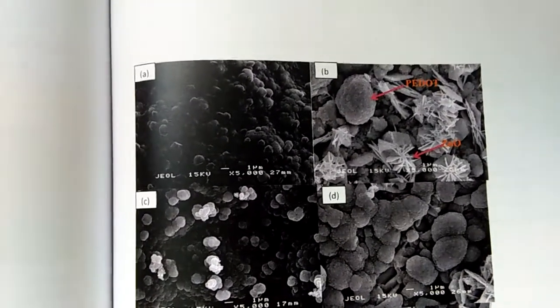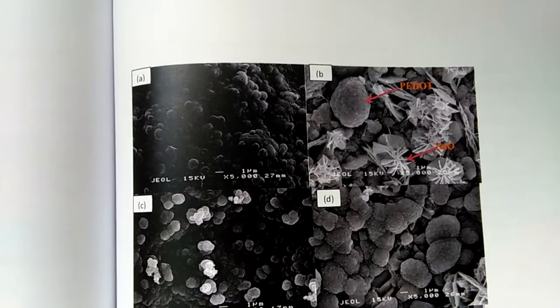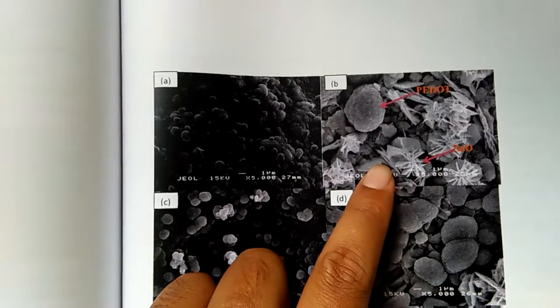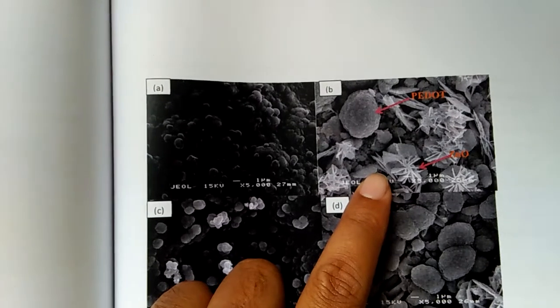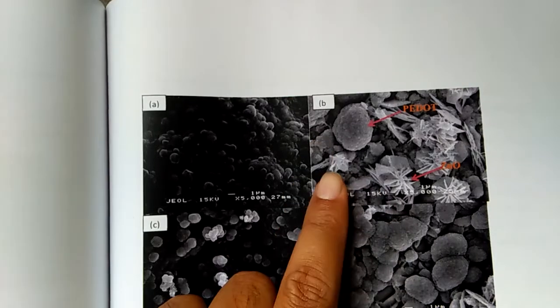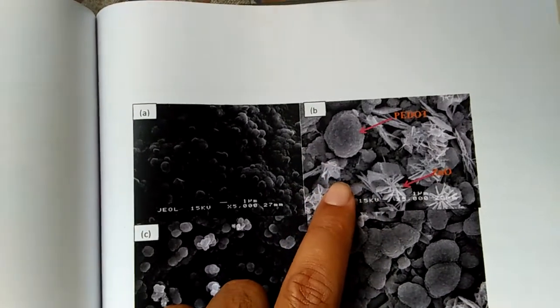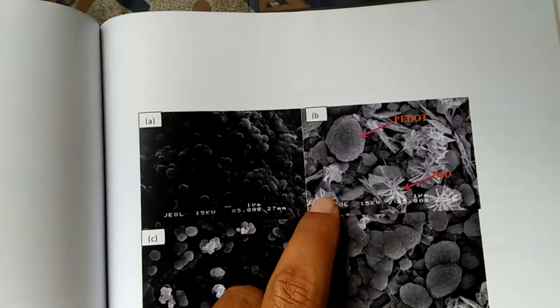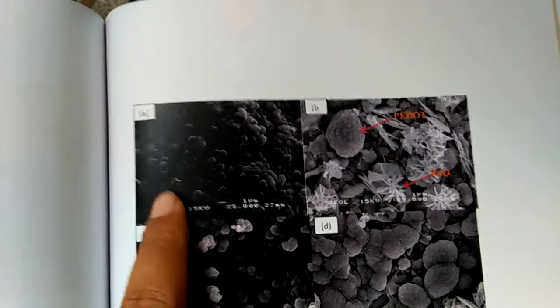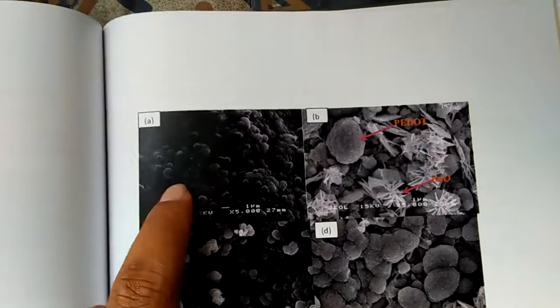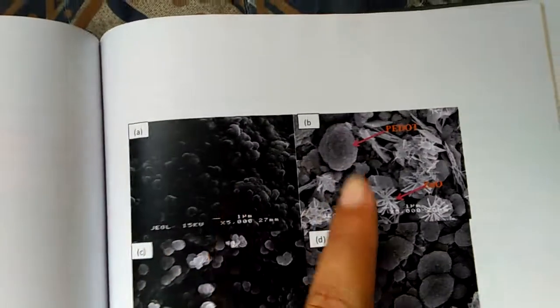The first one is, you prepare zinc oxide. You deposit zinc oxide using a water bath at 80 degrees Celsius, using a three-electrode system, and prepare the zinc oxide first. And then, using the zinc oxide on the ITO as a substrate, you deposit PEDOT on top of it. So next, you can get this structure, a combination of PEDOT zinc oxide.